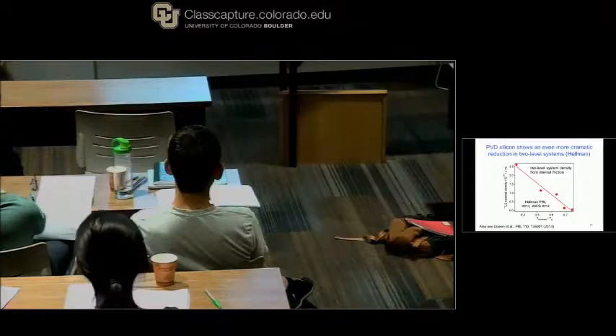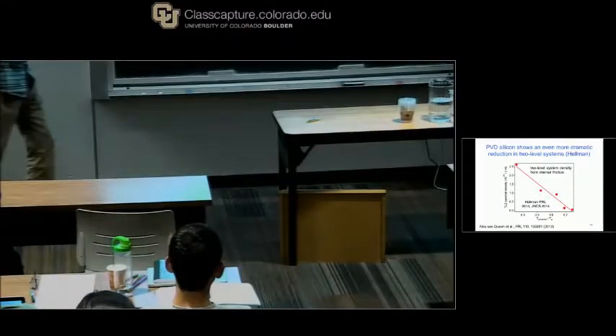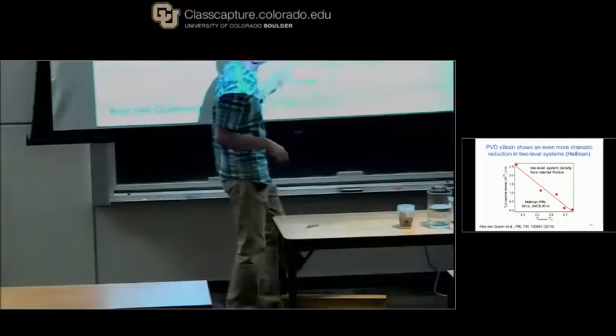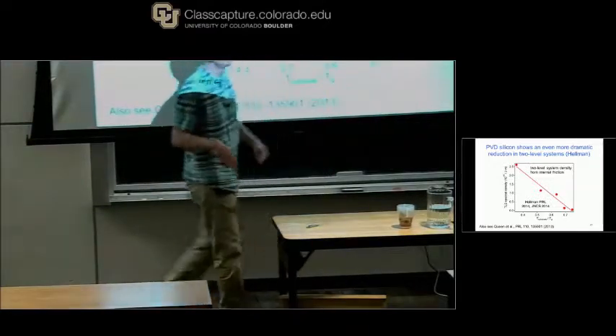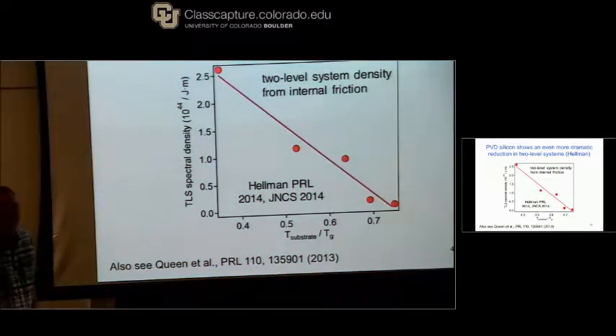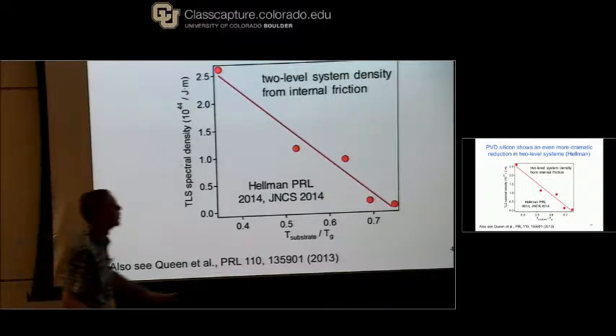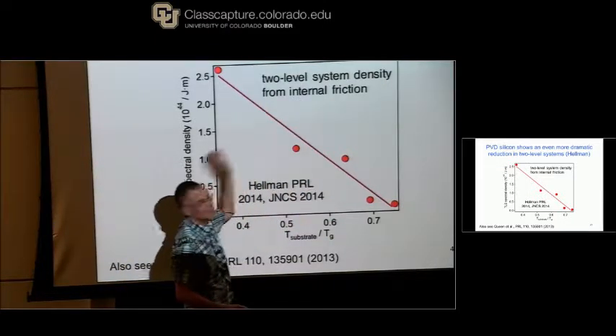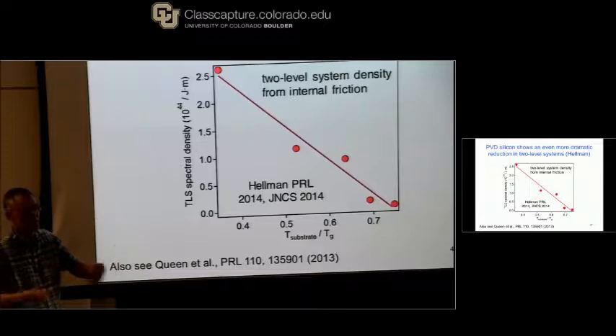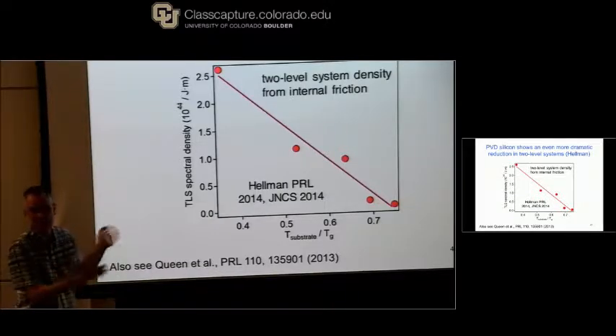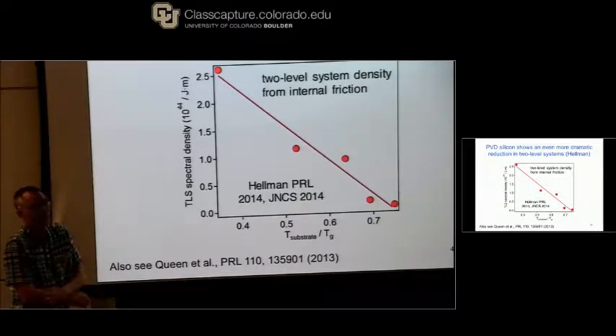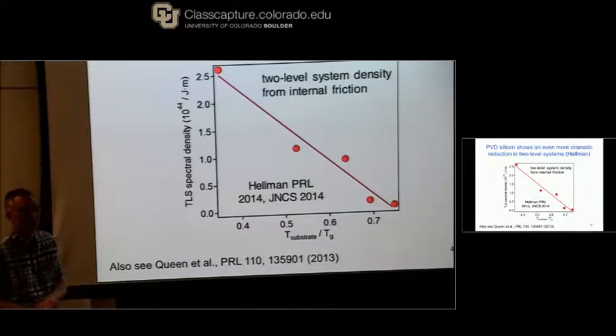And what's the other point? The other important point is that as you go towards 0.85 Tg, the density is getting lower and lower and lower. Now, at this point, we don't know the kinetic stabilities of these samples. And so there's a lot of additional experiments that you would need to know whether this really fits into the same pattern. But I think it's, at a minimum, here are two important examples of how non-universal the low temperature properties are of amorphous systems.